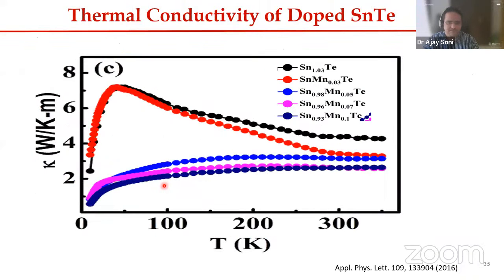Okay, but the interesting aspect here is the lattice thermal conductivity. If you look here, this is the usual pattern for the lattice thermal conductivity of solids. You have a peak which represents the scattering, the interaction of the electron phonons. Okay, and this peak shows that it is a perfectly crystalline solid. But if you do not have this peak, if you end up getting this kind of behavior, that means it shows a glassy behavior in the material.